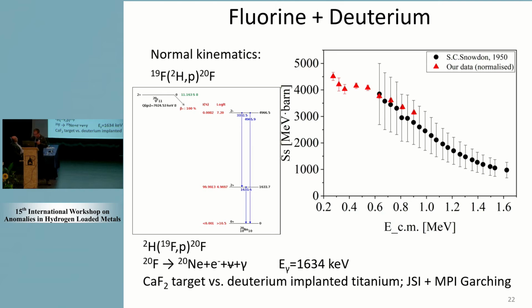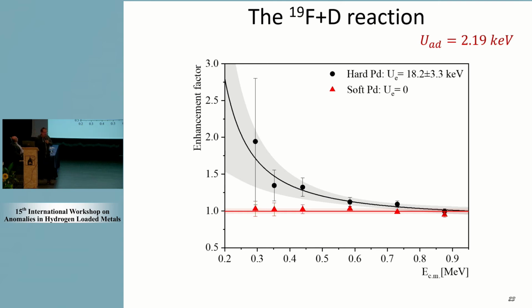So by knowing then the bare cross-section, we could study the inverse kinematics reaction, where we expect electron screening. So this is what happens. In hard palladium, we determined 18.2 keV for the electron screening potential. The adiabatic limit is 2.2 keV. And on the other hand, in soft palladium, we didn't get any electron screening, which also says that we deduced the cross-section well in normal kinematics.